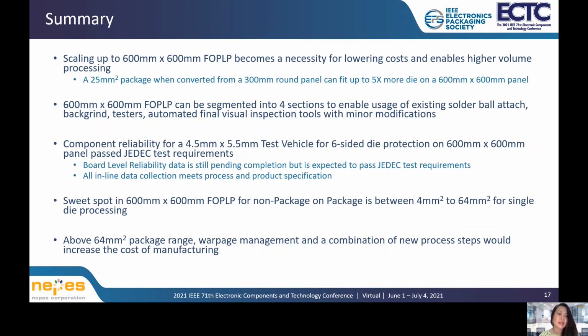In summary, scaling up to 600 mm by 600 mm fan-out PLP becomes a necessity for lowering down costs and enables higher volume processing. A 25 mm squared package, when converted from a 300 mm round panel, can fit up to 5 times more die on a 600 by 600 mm panel. 600 mm by 600 mm fan-out PLP can be segmented into 4 sections to enable usage of existing solder ball attach, back grind, testers, automated final visual inspection tools with minor modifications.